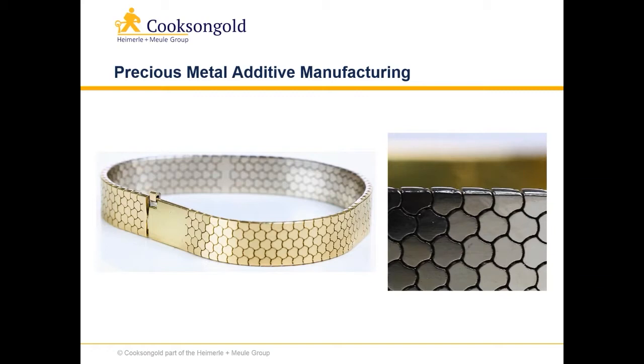So the part that you're seeing on screen at the moment is an 18-carat bracelet that was printed in 3 sections, just because of the size of the build area that we have, and the guys will go into more details on that later. But it was printed in 2 colours. So we printed the first half of the bracelet in 18-carat yellow gold, stopped the process, removed the 18-carat yellow powder, and then continued printing in 18-carat white gold. So you have a bi-colour bracelet, one on top of the other. And once again, the guys will discuss how that's possible during the brief a bit later.